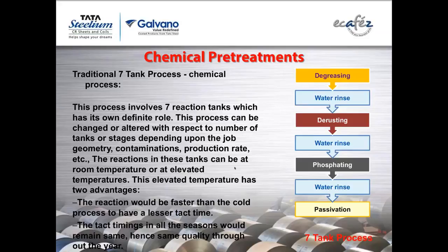Now why this passivation is there after phosphating: phosphating is actually a crystalline structure, and these crystals are usually needle shaped. So there could be some gaps or micro gaps within that crystalline layer. This passivation layer is going to temporarily close those. Now one more question is how much time I can have between phosphating, this total stage, and the first coat, primer coat or first application coat or powder coat. Usually depending on weather, if the humidity is below 80%, you can wait up to 8 hours. If it is more, less than 4 hours.